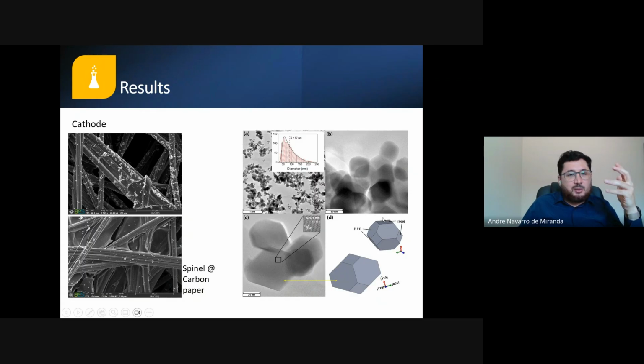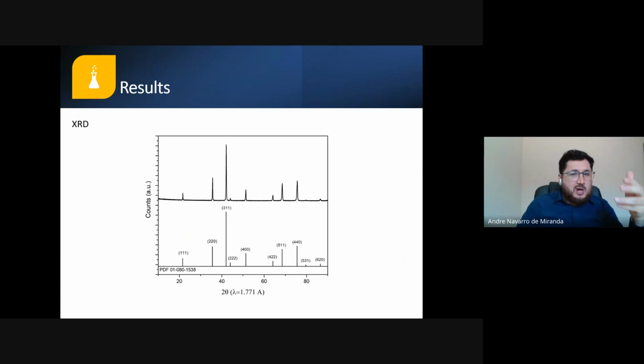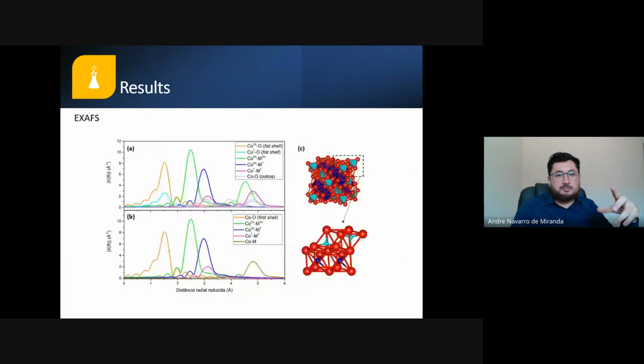And when we look at papers, we see that the active surface of this catalyst is the 111 surface. 100 is not that active. So we started to understand why this catalyst is active, and we started to study this 111 surface. So we did X-ray diffraction, and we could see that it's a really crystalline material. It's not amorphous. So although it has these three different kinds of cation, it's just one phase, the spinel phase, and it's really crystalline.